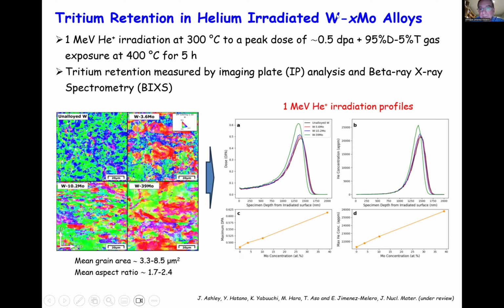So what we did in that case, with another PhD student, was look at tungsten-molybdenum alloys, not tantalum but another element, to see if that helps or not. We irradiated those materials with helium at 300 degrees up to a damage level of 0.5 dpa. Once the material has some of those bubbles and damage, we expose those materials to a deuterium-tritium gas at 400 degrees for 5 hours. We wanted to see if just having helium and lattice damage would make things worse in terms of retaining the tritium, which is something we don't want to retain because we need it for the fuel and because it's going to cause activation problems for decommissioning.